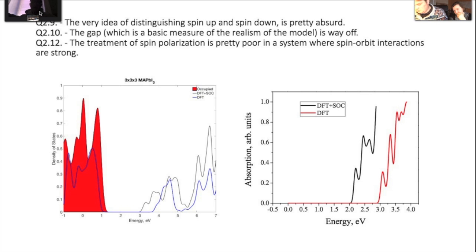And so what happens is what we would also expect. You have a closing of the band edges, which is also seen in other calculations. But now, if you take band gap values, instead of going from about 1 eV to close to 4 eV, a large band gap of almost 3 electron volts, now you have something that runs from 3 eV all the way back down to a little below 1.5, and the experimental is somewhere around 1.65, 1.7. So the spin orbit coupling definitely closes down the gap to what we would expect it to be.